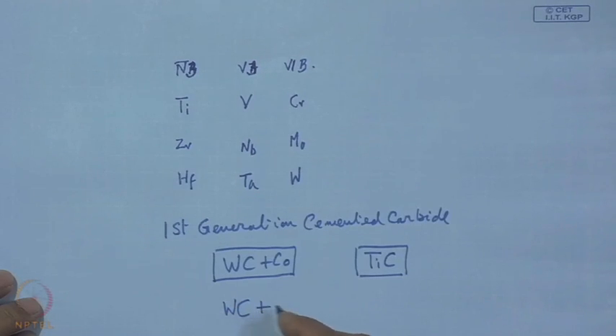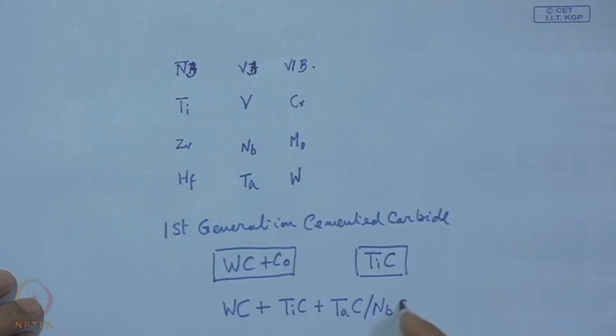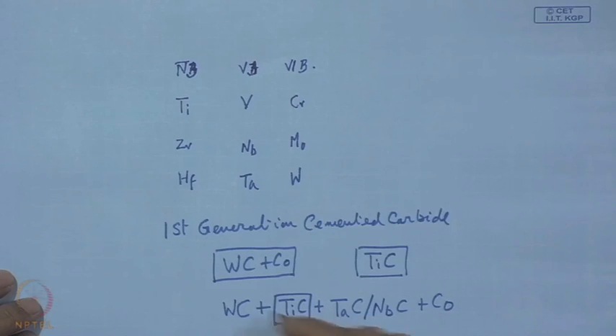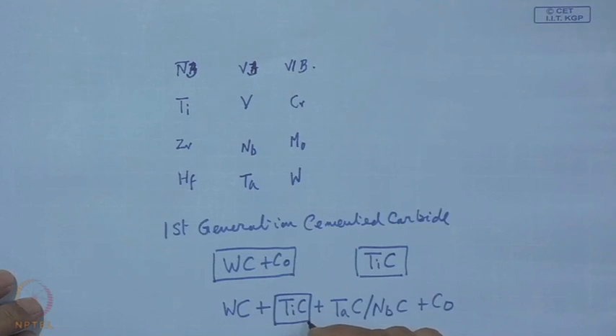This became the new formulation: titanium carbide plus a little bit of tantalum carbide or niobium carbide, plus cobalt. TiC becomes the strategic material when the cemented carbide tool is engaged in machining steel. TiC happens to be more wear-resisting during machining of steel, which is a long-chipping material. TiC has an anti-welding character and resistance against possible diffusion across the tool to the chip material.